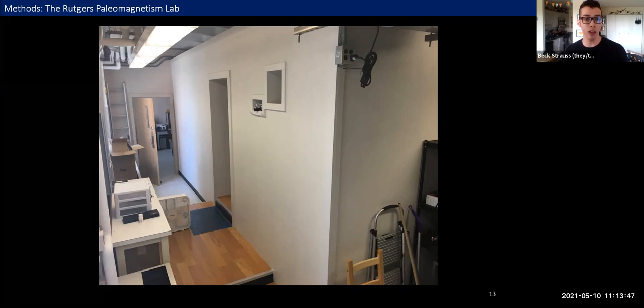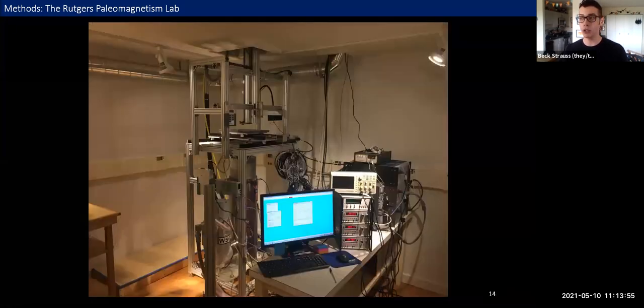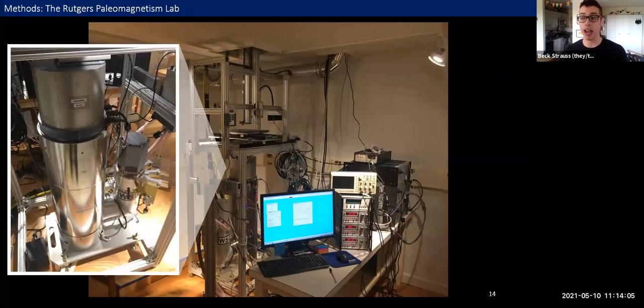So if you walk up the steps to get inside and you leave your keys and phone and other magnetic paraphernalia outside the door, when you walk in, you see our 2G squid magnetometer. This is a supercooled magnetometer that's capable of taking very, very sensitive measurements. When you step up onto the platform behind the magnetometer, you can see the actual instrument stack. On top, we have a degausser or AF coil, which can apply alternating fields to our sample to demagnetize it. I'll come back to that in a second.